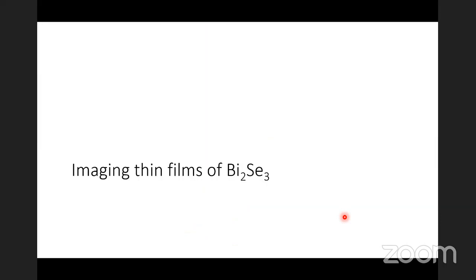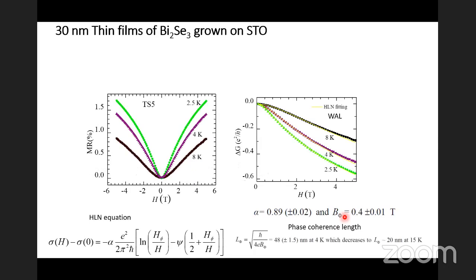So let us look at Bi2Se3 thin films first. We grew Bi2Se3 thin films on STO substrate, and you can do magnetoresistance measurements, and these measurements show very nice weak antilocalization. You can do a fitting through the popular HLN equation, and you can get the phase coherence length. The phase coherence length is about 48 nanometers at 4K, and decreases to about 20 nanometers at 15K. They were stoichiometric as well as epitaxial films that we obtained on Bi2Se3.